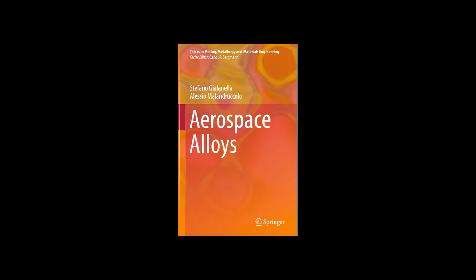And how do they put these coatings on? Our source mentioned thermal spraying. Thermal spray is a big category. Techniques like plasma spray and HVOF, high-velocity oxyfuel, all basically involve melting a feedstock material, powder or wire, and spraying the molten or semi-molten droplets at high speed onto the part surface, where they flatten out and solidify to build up the coating. How does this stick? It can be a combination of mechanical interlocking with the surface roughness, some diffusion bonding at the interface, and sometimes chemical reactions. And vapor deposition.